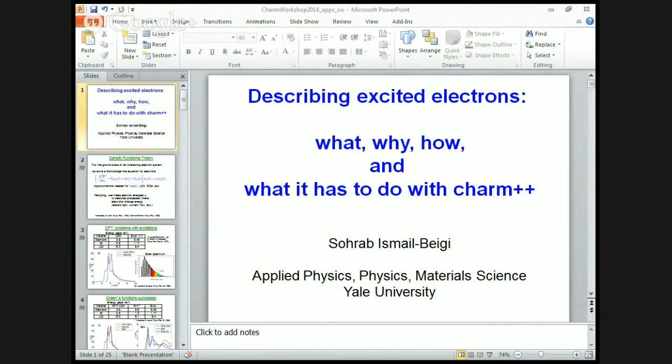There's some potential, like there are wells around the nuclei, so the electrons go there, and they make bonds between them, and it's described by a single potential. And so you solve this thing, and you have to do it self-consistently, and for large systems, it's very challenging. That's why OpenAtom took a while to develop, okay? But in the end, this is what you're doing. And then you can get many things out of this. And you have to make some approximations. So this potential here, nobody knows what it is, so you approximate it. But the structure is like this.